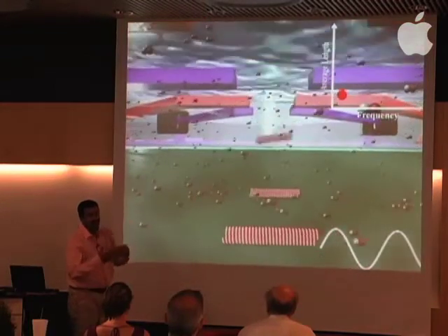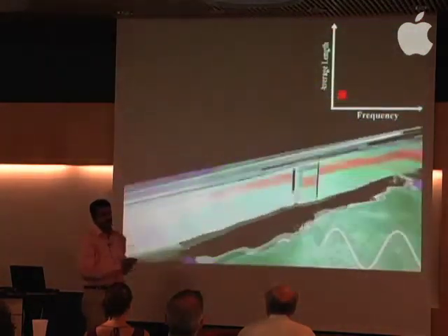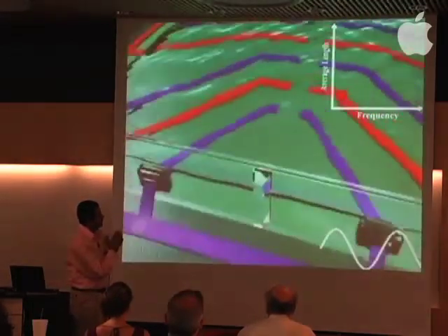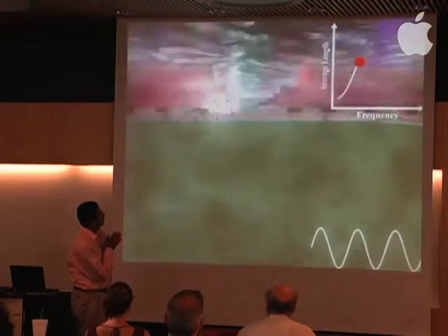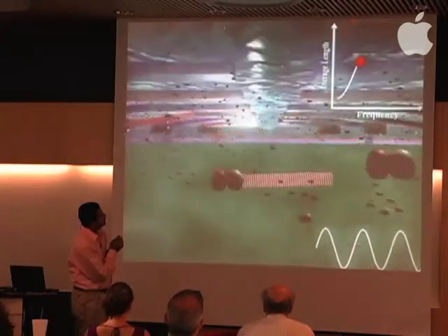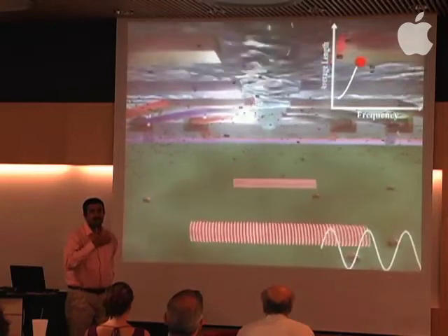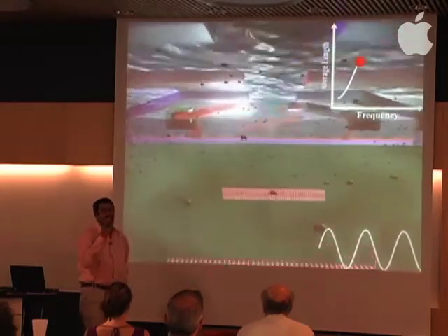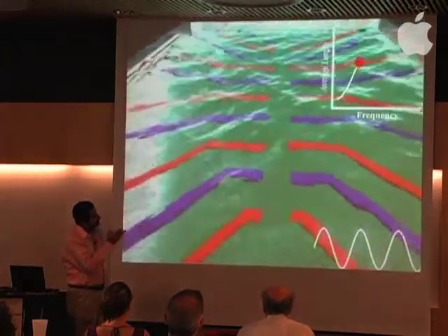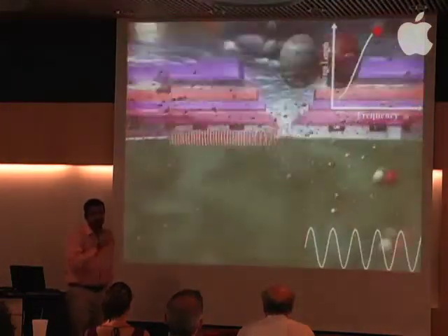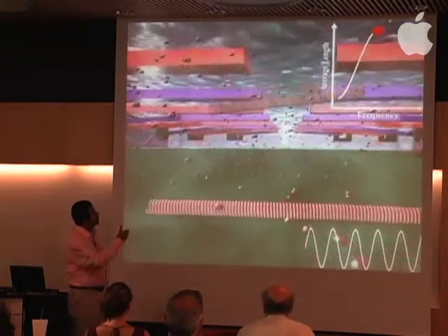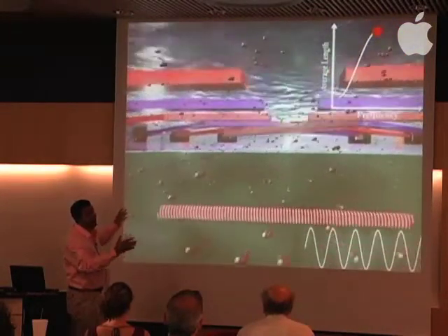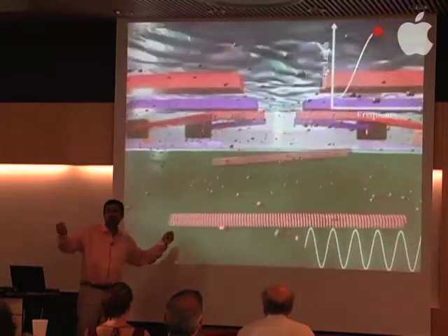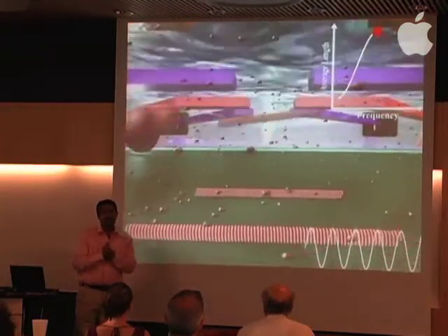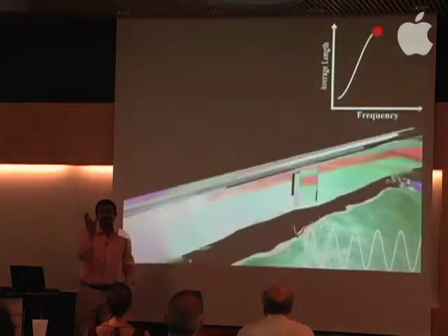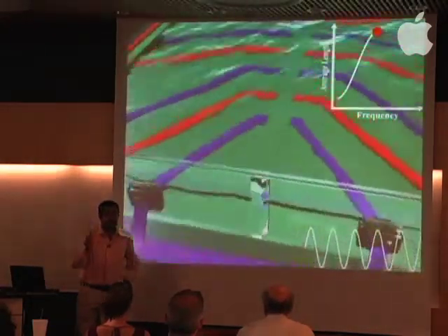So we started from very low frequency to the very high frequency regime, and we measure the length of the microtubule that we get. And we find that as frequency increases, as we come to the megahertz, if you are at the very low frequency range, of course you get something. But as soon as you come to the megahertz range, the whole scenario goes on changing. You increase the frequency and you find slowly larger and larger microtubules. Initially, suppose you apply a few kilohertz signal, you will get microtubules a few hundred nanometers long, say 200 nanometers. It's a very small length.